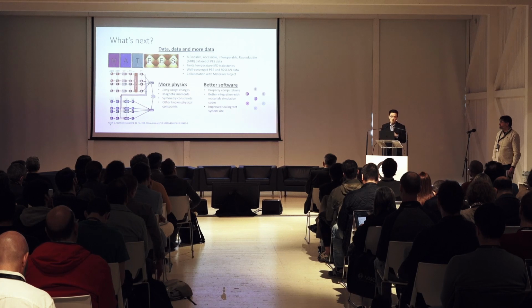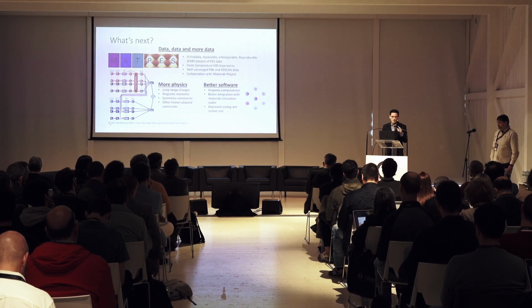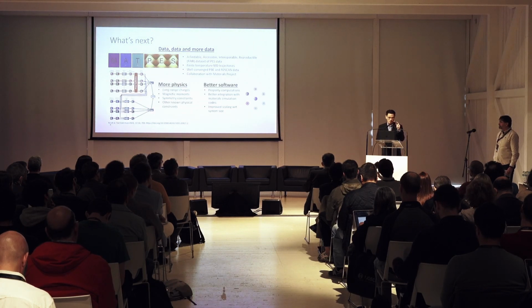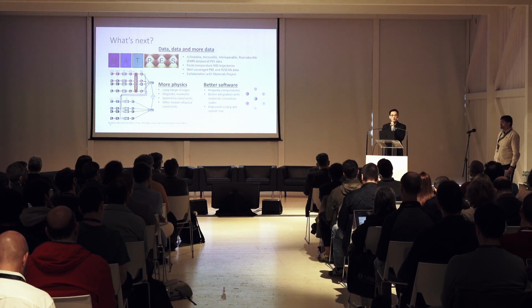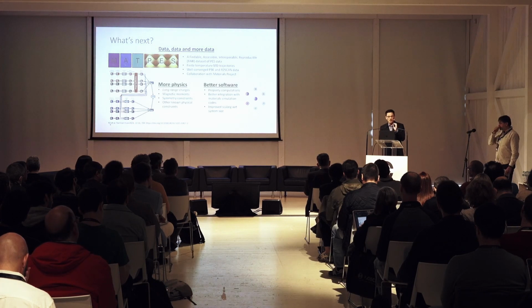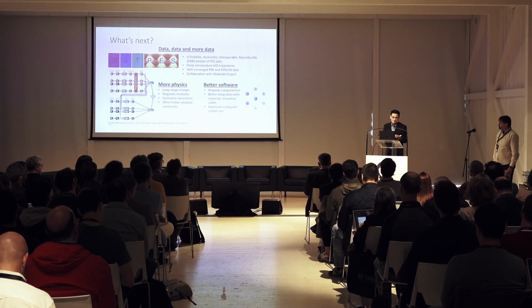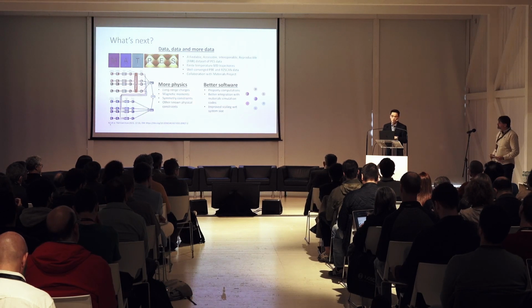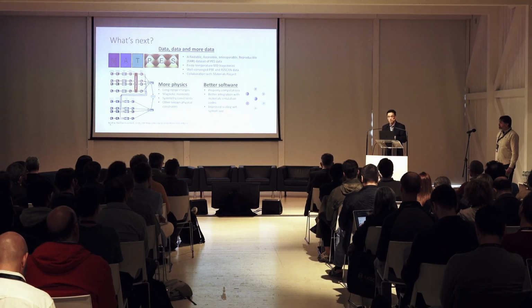Now, one thing that we have noticed is that it is a bit surprising, the different models, some of them may have technically lower energy and force errors, but it turns out that they are much less stable. So there is some inherent trade-off between how low your energy and force errors are versus the stability of the calculations. So yeah, that would be my rule of thumb. I honestly don't think that there is a gigantic difference between, say, MACE versus M3GNet in terms of actual architecture and errors.